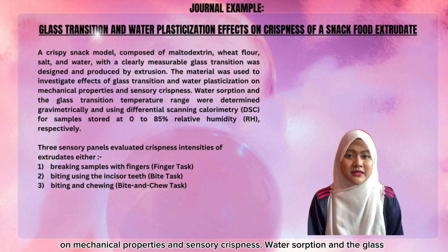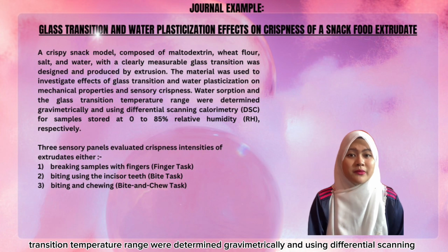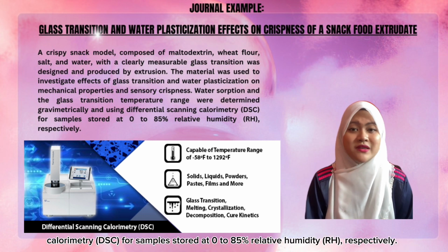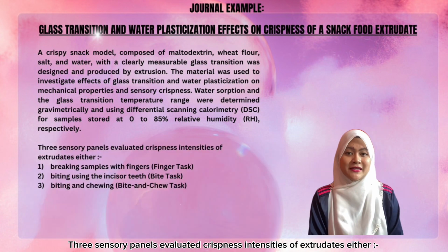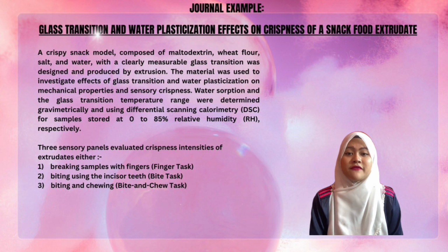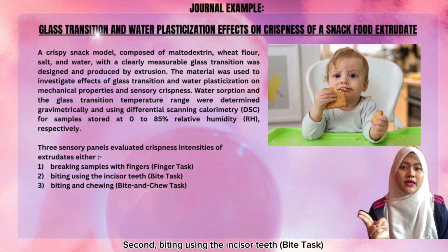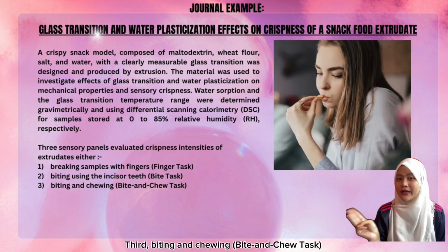and sensory crispiness. Water sorption and the glass transition temperature range were determined gravimetrically and using differential scanning calorimetry (DSC) for samples stored at 0 to 85% relative humidity (RH) respectively. Three sensory panels evaluated crispiness intensities of the extrudate. First, breaking the sample with fingers, the finger task. Second, biting using incisor teeth, the bite task. And third, biting and chewing, the bite and chew task.